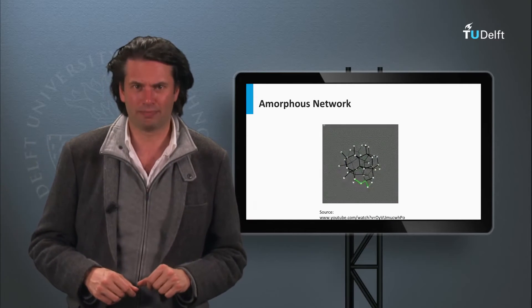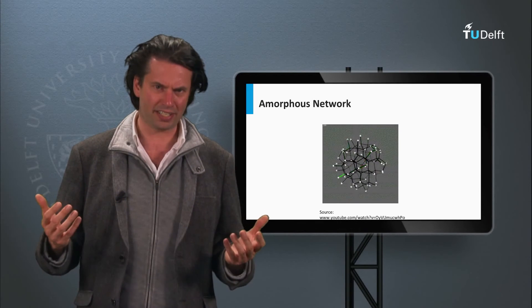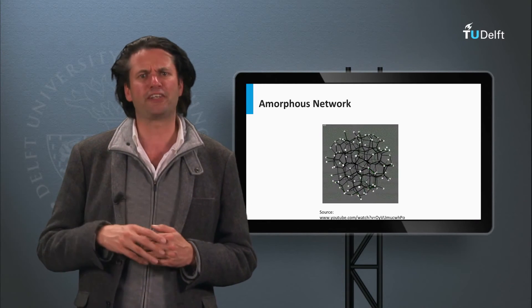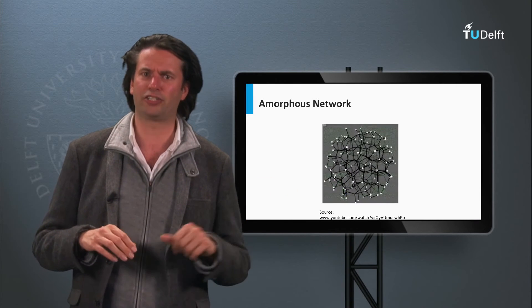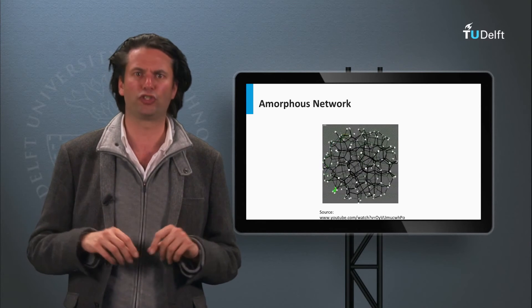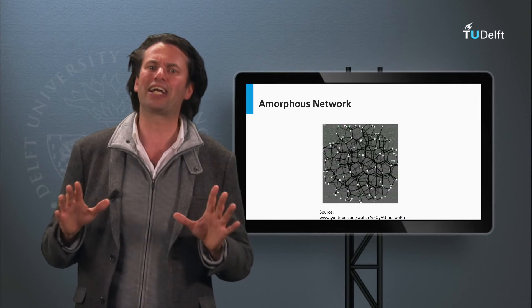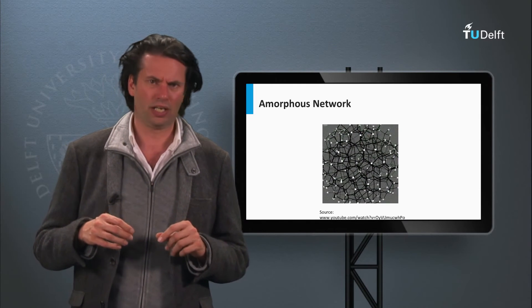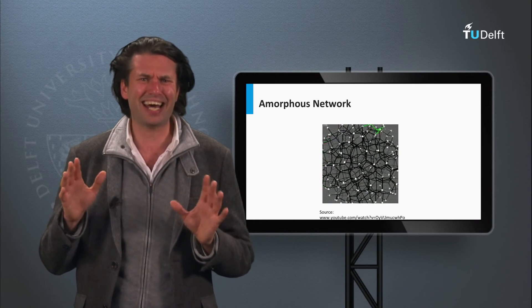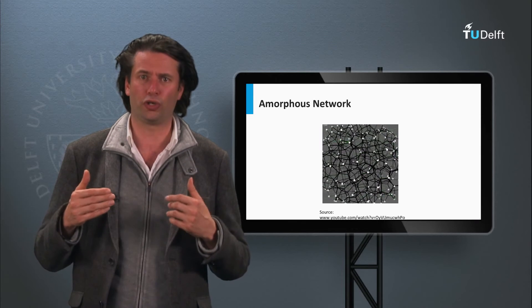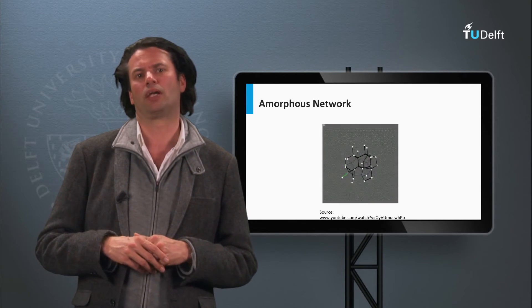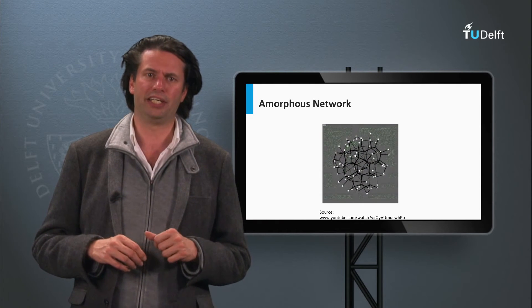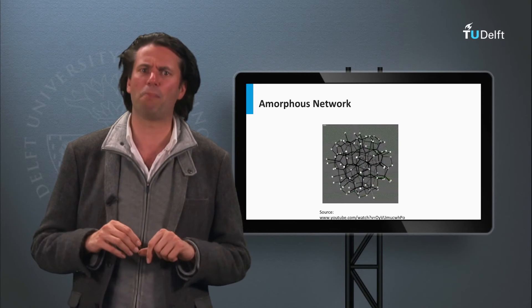How does an amorphous lattice look like? Crystalline silicon has an ordered lattice in which the orientation and structure is repeated in all directions. For amorphous silicon this is not the case — the lattice is disordered, forming a so-called continuous random network. On atomic length scales, also called short-range order, the atoms still have a tetrahedrally coordinated structure, with bond angles and bond lengths slightly distorted relative to crystalline silicon. However, at larger length scales, or long-range, the lattice does not look crystalline anymore — only a disordered network of silicon atoms is seen.